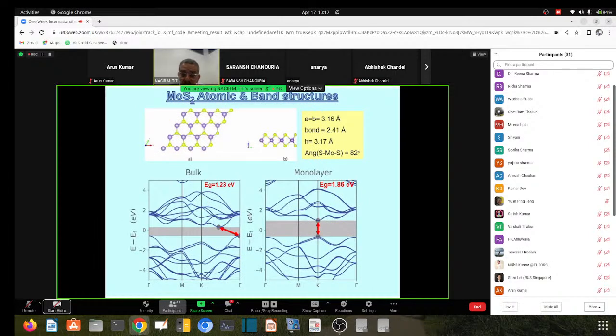The band structure of the MoS2. Well, let's start from the atomic structure. Here I showed only the picture of the one monolayer. The yellow color is sulfur, the purple is molybdenum. The molybdenum is under trigonal prismatic symmetry, where it has six sulfur neighbors around it, and the sulfur is under what we call pyramidal symmetry, with covalent bonds with the metals. The lattice constants a and b are 3.16, the bond length is 2.41, and the thickness of the monolayer is 3.17.